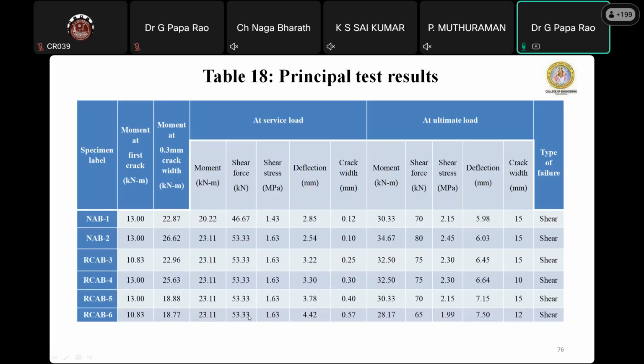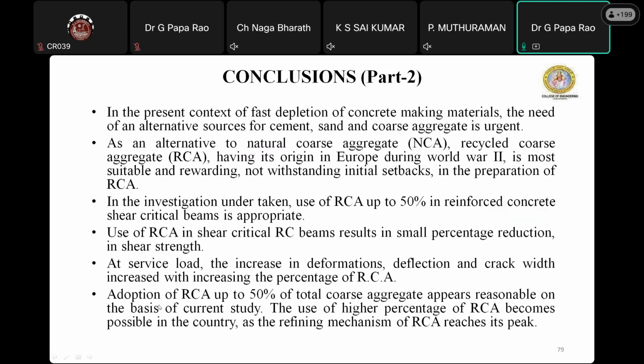If the percentage of replacement is more, our deflection values and crack widths are also slightly increased. Therefore, we can limit our recycled coarse aggregate to up to 50% from our observations. Adoption of recycled coarse aggregate up to 50% of total coarse aggregate appears reasonable on the basis of the current study. The use of a higher percentage of recycled coarse aggregate becomes possible in the country as the refining mechanism of RCA reaches its peak. If we make sure that our refining mechanism is large scale and well processed, we can use higher percentages also. But based on our observations, we suggest up to 50% replacement of natural coarse aggregate with recycled coarse aggregate is reasonable based on our current study.